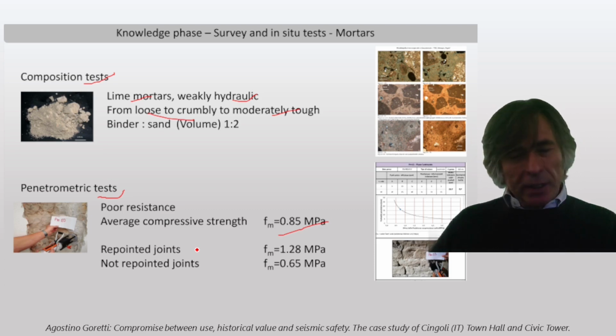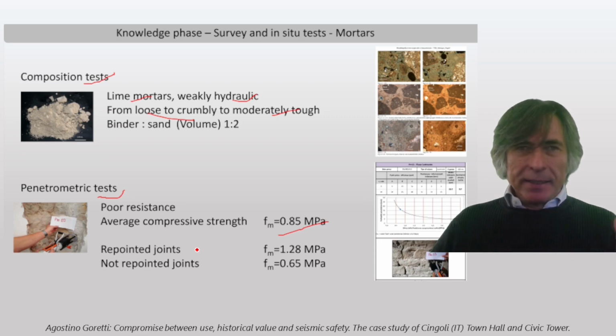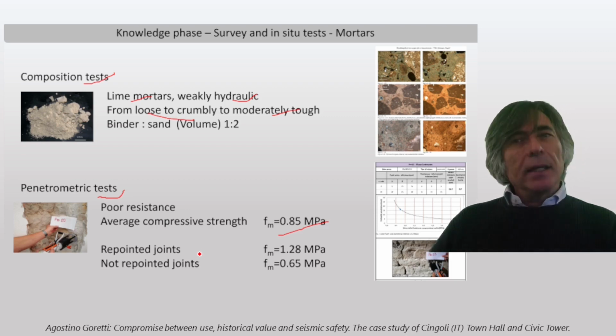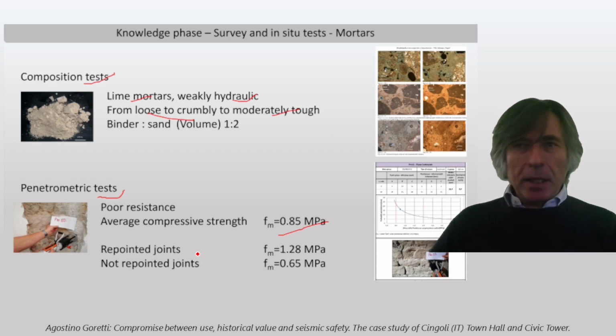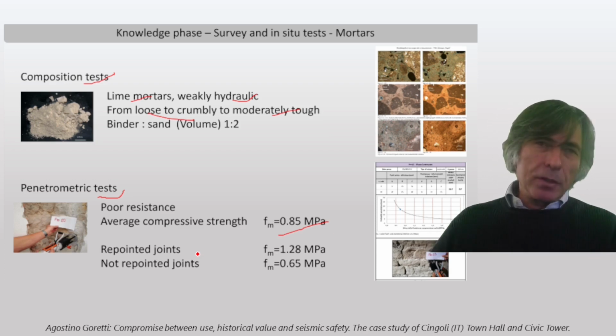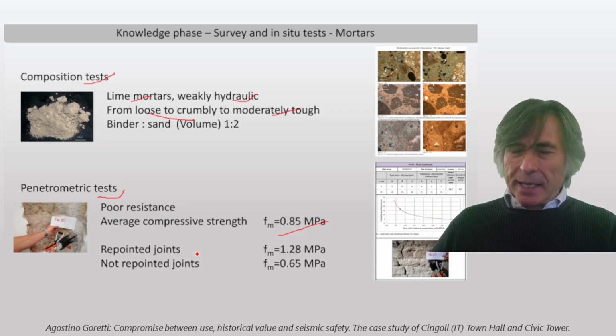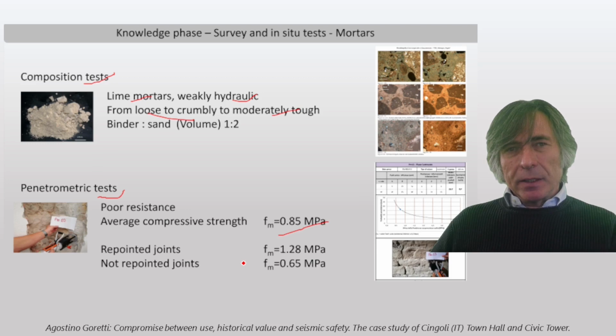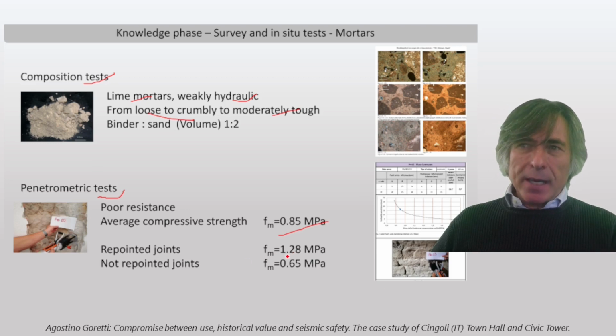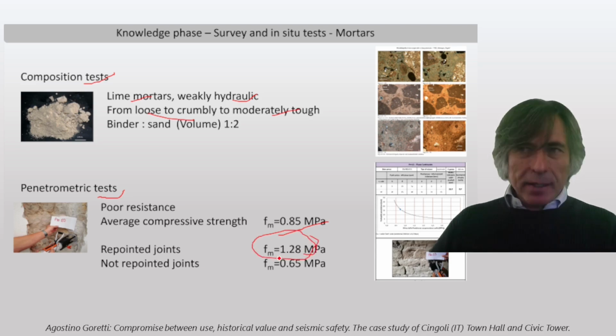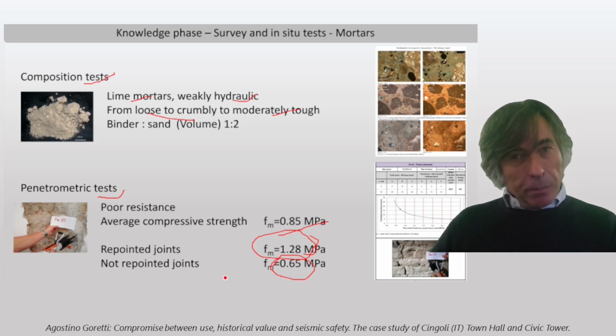Always remember to take the results of the test and make some analysis of your own on this test. I separated the repointed joints from the not repointed joints according to the information that I had, and if the resistance is averaged over only the repointed joints, the resistance becomes 1.2, so increased, while it decreased to 0.6 megapascal for the not repointed joints.